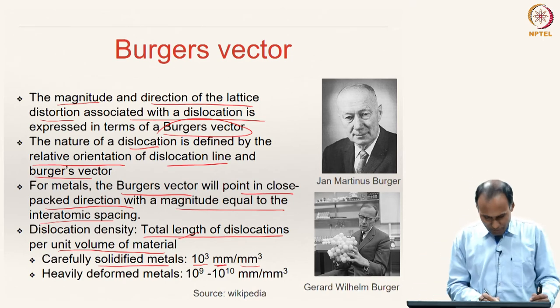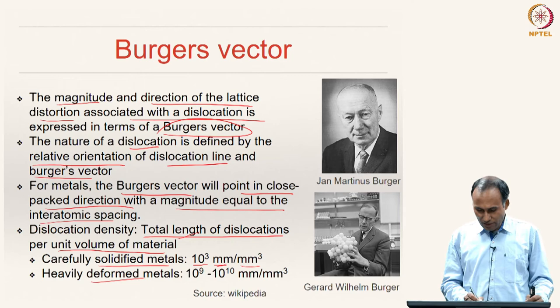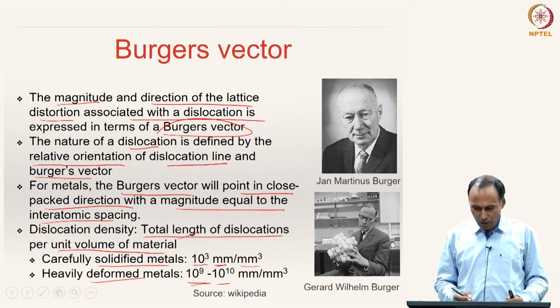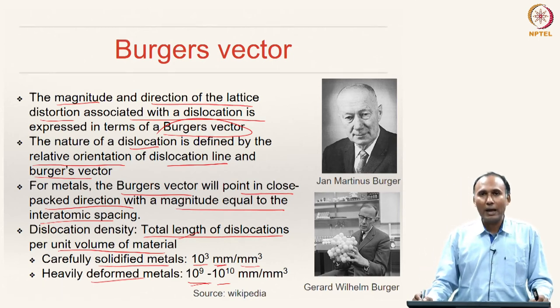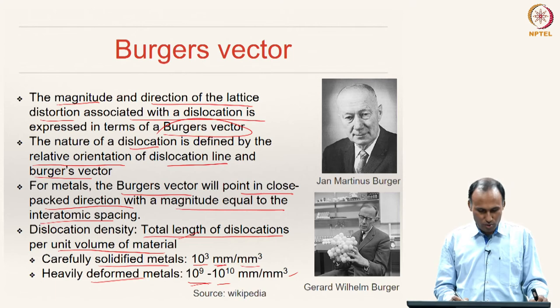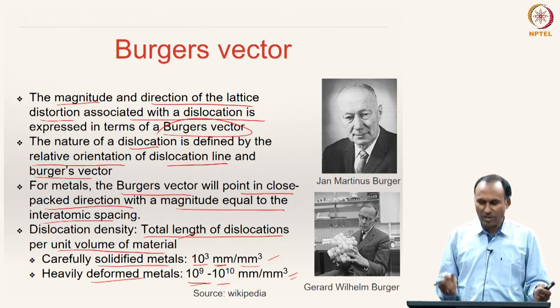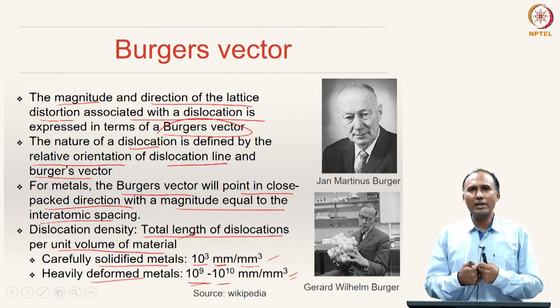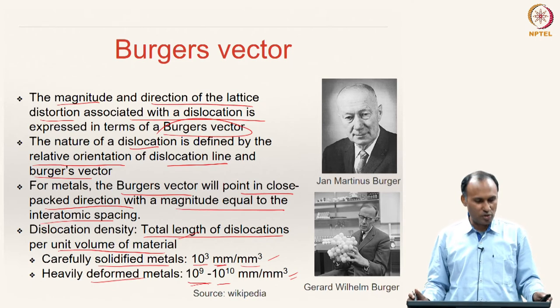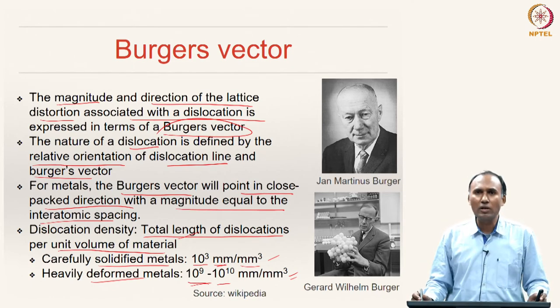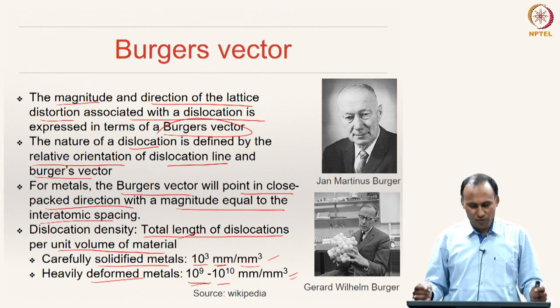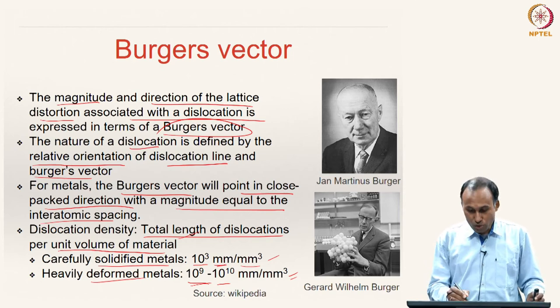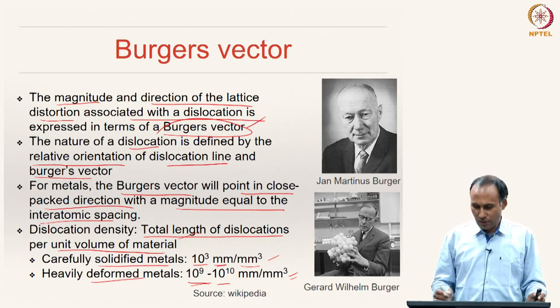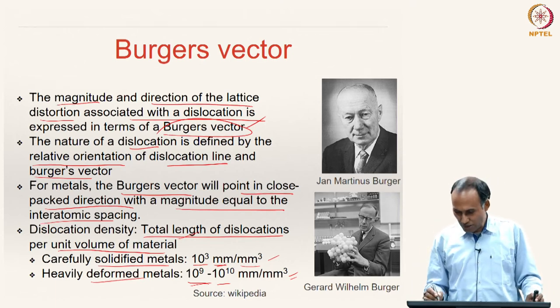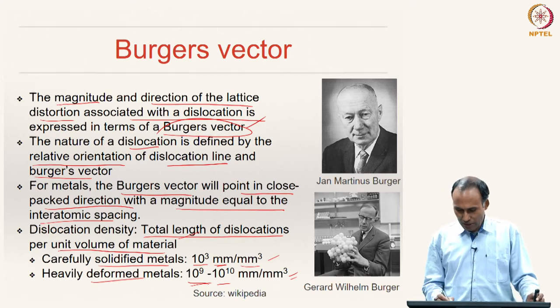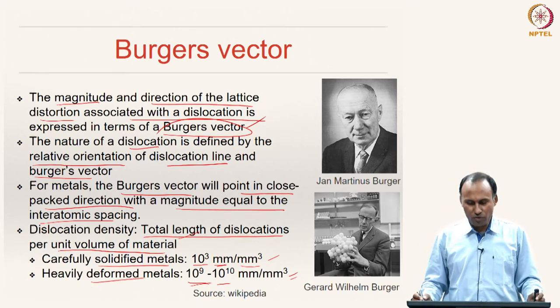If you have a heavily deformed material, such as heavily deformed metals, then the dislocation density is going to be very, very high. You can see almost 10 to the power 10 mm per cubic mm. So extremely high, almost 6 orders of magnitude from the carefully solidified material to the extremely deformed material. That means during deformation, the dislocations multiply significantly, increasing the density of dislocations significantly. Now, the persons responsible for the description of the magnitude and direction of lattice distortion through the Burgers vector: the concept of the Burgers vector was invented by two brothers, two professors at Delft University, Johannes Martinus Burgers and Wilhelm Burgers. These two people are responsible for the definition of this Burgers vector.